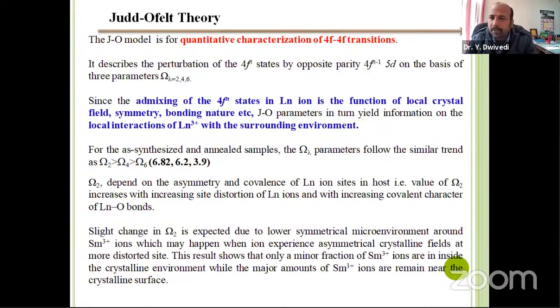Since this admixing of 4F family levels with 4F levels is a function of the local crystalline field, the symmetry, and the bonding nature, the local microenvironment near this doped ion, these 3 parameters, omega 2, omega 4, and omega 6, actually represent the local interaction of lanthanide with the host. In case of glass and glass ceramic, we find the same trend: omega 2 is more than omega 4 and omega 6.